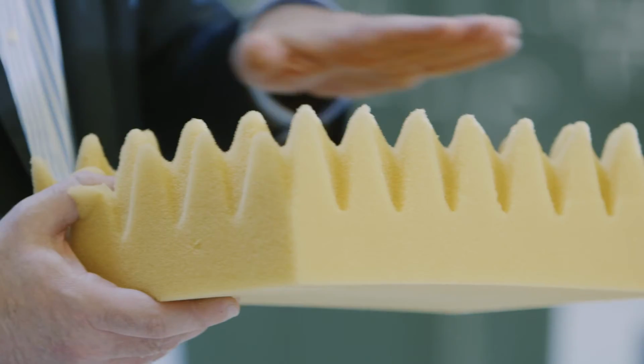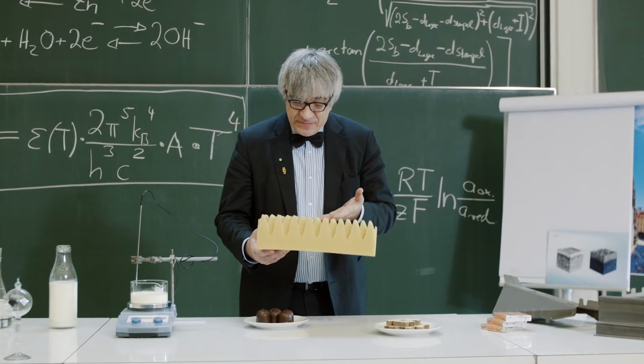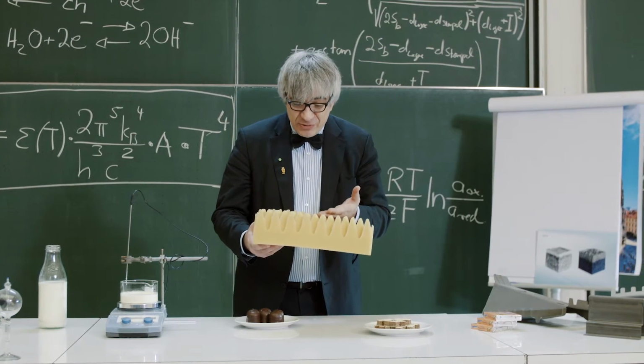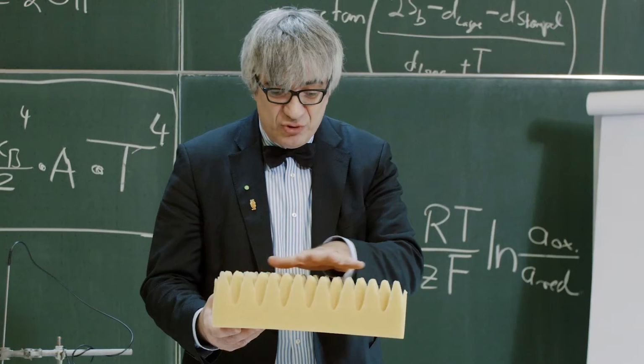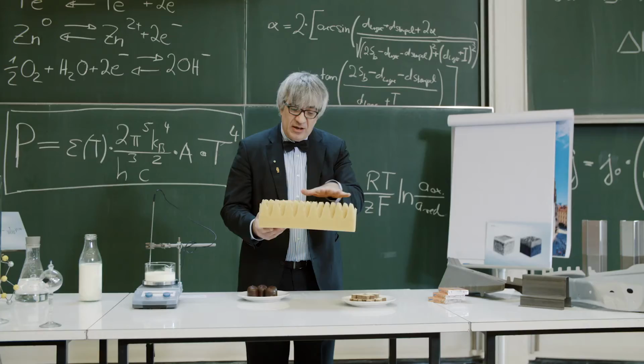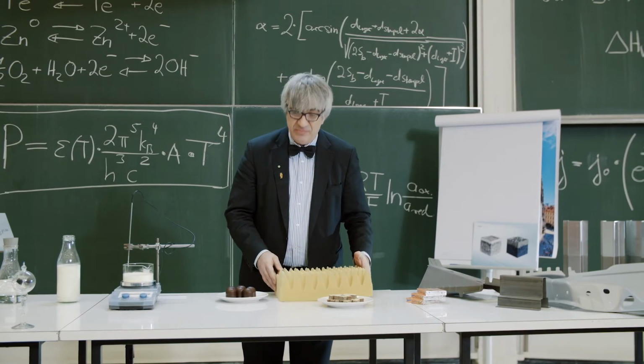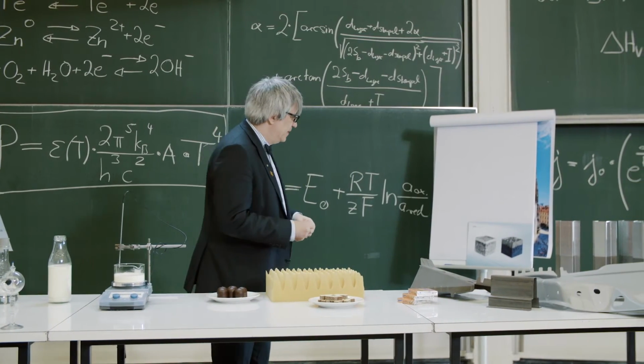When we take a close look at this PHS production process, we see that iron-zinc crystals form from below and grow into the coating layer. These crystals create a rough surface that prevents the liquid zinc from flowing off. We can illustrate that with a drawing.